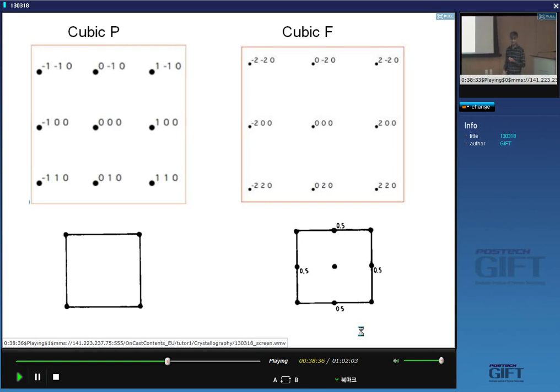Okay? So here, notice this is 200 and not 100. In this case, the symmetry of the pattern is still exactly the same. So the only way you recognize that it's 200 is by measuring the d-spacing. Is everyone happy with that? So I've shown you in a simple way why the 100 reflection is missing. We've got a set of scattering centers halfway, which will scatter half a wavelength out of phase, and therefore you do not get 100.